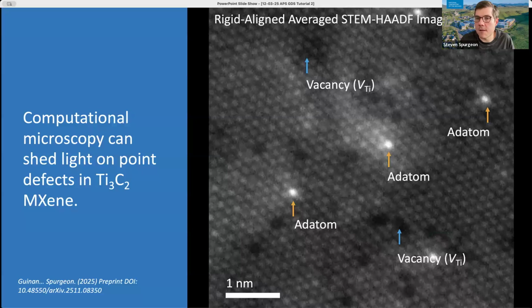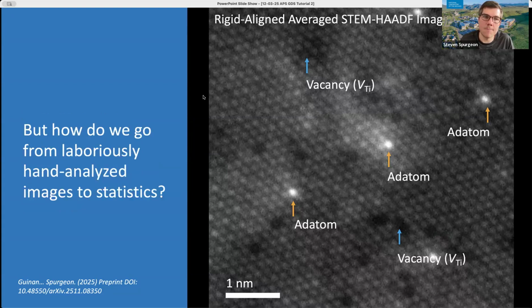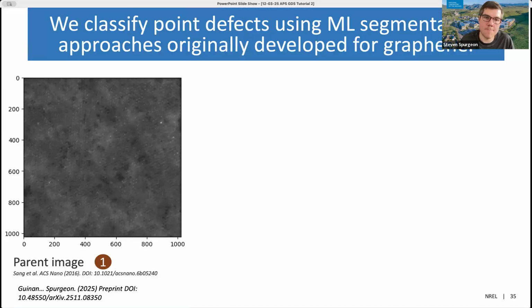But quantifying these defects is incredibly challenging, again, because we have to do so much averaging, or we have to be able to look at very noisy, low-dose data in some kind of statistical and scalable way. So the question here is how do we go from a very traditional human-in-the-loop workflow to one that employs machine learning to get better statistics and ultimately better describe the population of defects in the MXenes. We can use machine learning here and actually use models that were developed originally for graphene and adapt them to the MXene problem.